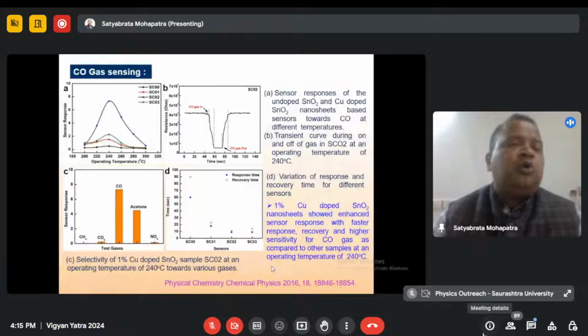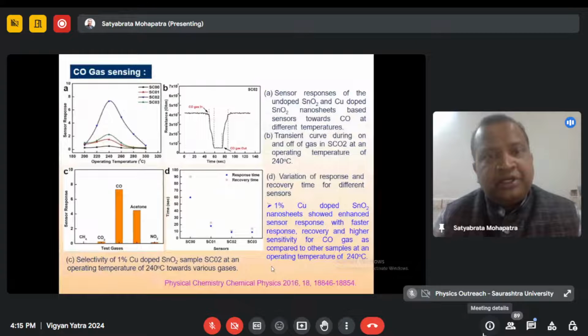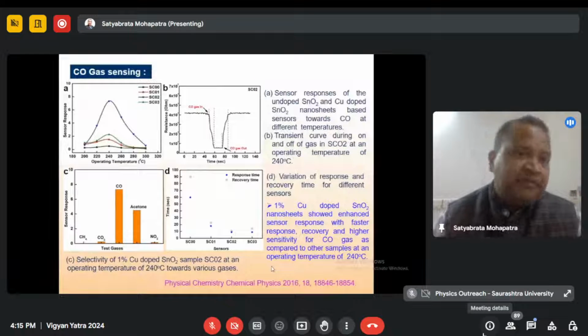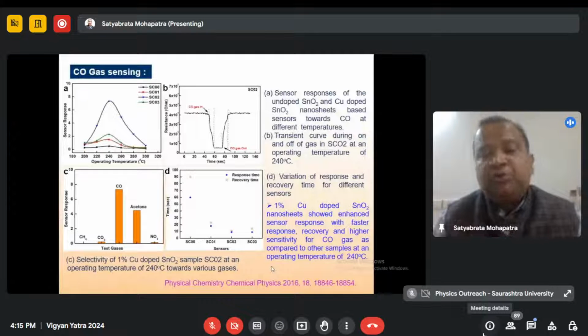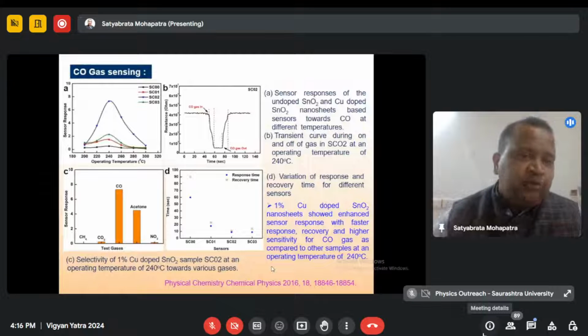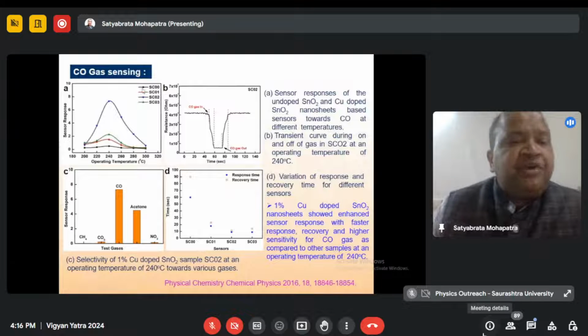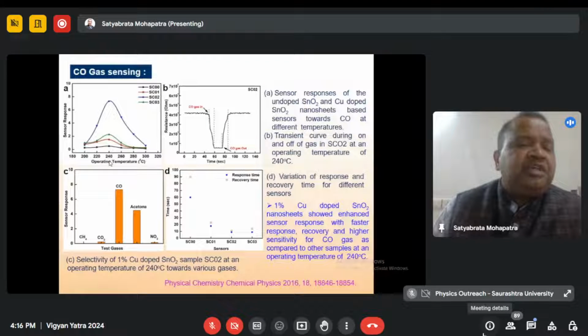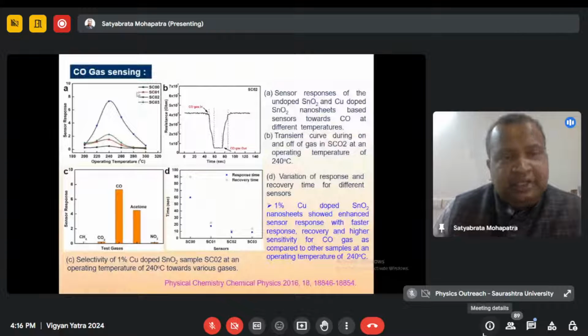Carbon monoxide is one of the most lethal toxic gases, which leads to a lot of deaths, and that's where it is important to develop efficient sensors with a quick response and recovery time. You can see that the sensors created out of this material showed a slightly higher operating temperature, 240 degrees centigrade. But on increasing the doping, you can see that SC02, that is 1% copper doping, leads to a maximum enhancement in the sensor response.